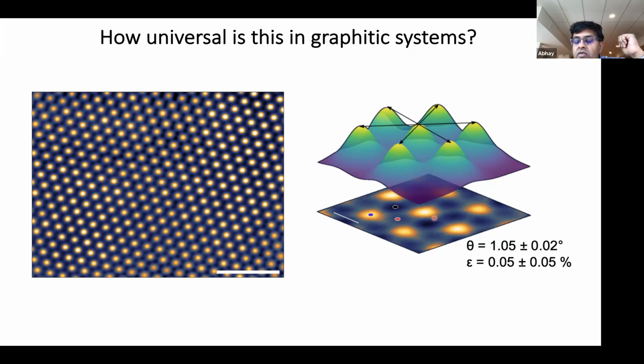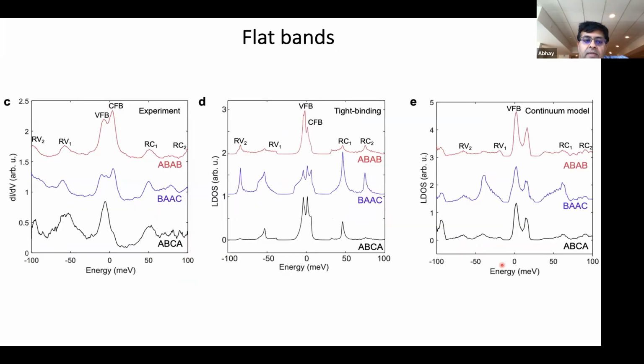If you calculate what the strain is just from looking at these Moiré positions, the experimentally measured strain in our samples is basically 0 within error bars. So it's 0.05% plus or minus 0.05%. So we're able to make clean samples where strain is basically negligible. What we first showed is that in this system, exactly like twisted bilayer graphene, there are the same types of flat bands. Here you see these flat bands that are present near the Fermi level, and then there's the next set of flat bands that are away, and then the various sub-bands as you go higher and higher up in energy.